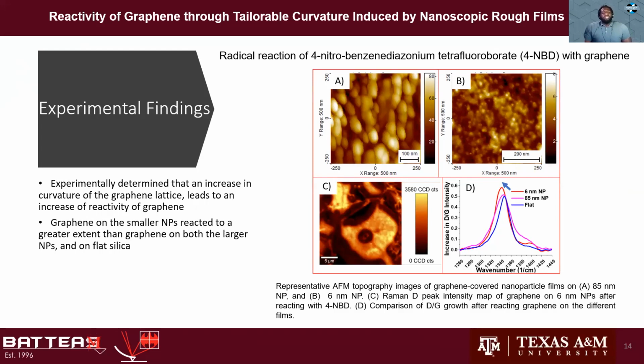And so to control the extent of out-of-plane strain in graphene, we transfer graphene to both flat silica films and silica films consisting of 6 nanometer or 85 nanometer nanoparticles, seen in figures A and B. The smaller the nanoparticles, the greater the adhesion of the graphene film, leading to greater curvature and increased lattice strain.